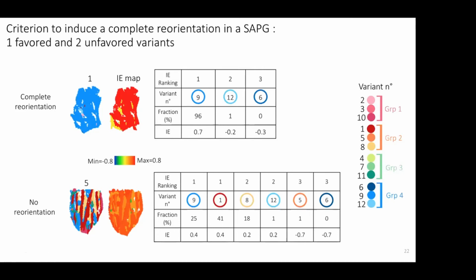By contrast, in grain number 5, we had two self-accommodating groups, group number 2 and group number 4. In group number 2, we have variants number 1, 8, and 5. Two variants have a positive value of the interaction energy, meaning that they are both favored, so they both want to grow at the expense of the others. We think that in that case, it will compensate. No one will grow at the expense of the others, but they can grow at the expense of variant number 5, because variant number 5 has a negative value of the interaction energy.